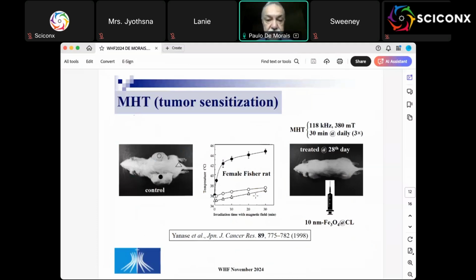And you can see in the plot how the temperature goes with the time of application of the AC field in minutes. They went up to 30 minutes. You can see that the temperature in the tumor saturates, is asymptotic around 45 C. So they performed the magnetic hyperthermia. This is the frequency of the field they applied, and the amplitude was 380 millitesla. They applied it for 30 minutes, like you can see in the plot, and 3 times a day. After 1 month of treatment, you can see both tumors completely removed from the body.